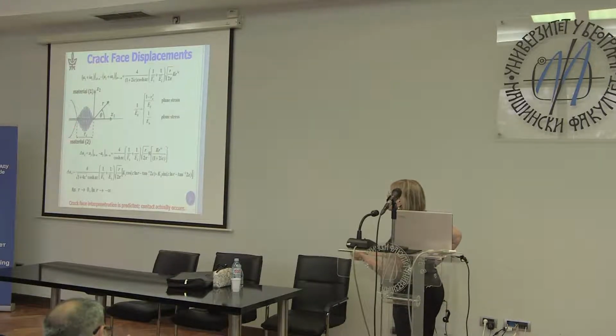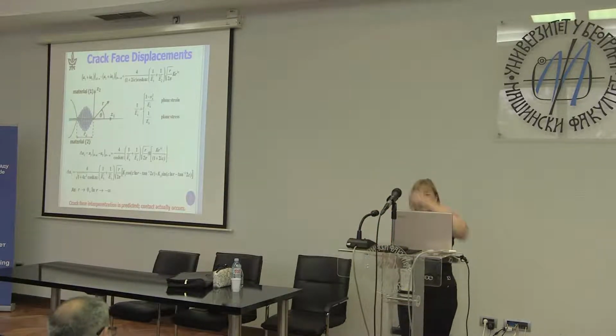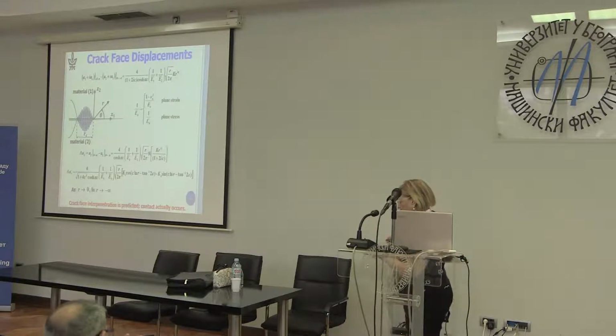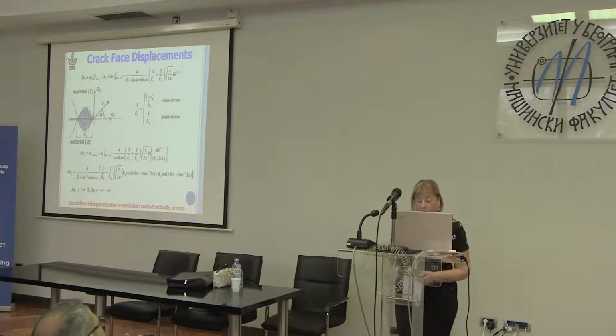Okay, so what I was talking about is we have an interpenetration zone, but eventually it ends and then the crack opens, and it really depends on the value of epsilon. Well, it depends on two things. It depends on the value of epsilon, and it actually depends on how much shear is in the problem. If you have just tension, a large body with an interface crack and you put the body in tension, this zone will be very small. But people didn't know that, I think, initially, and so this interpenetration zone really was very troubling at the beginning.